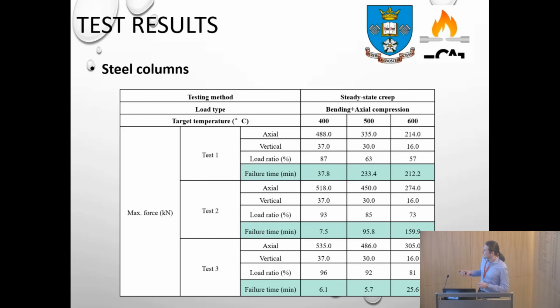You can see the columns, all of the columns that were tested failed within the 240 minute interval during the tests. And if the load ratio was close to or above 90% of the capacity force, the failure time was quite low during the tests, as you can see from the table here. If you lower the load ratio, the failure time also increases. So this is the representation of a total of 9 tests that we did in Split.